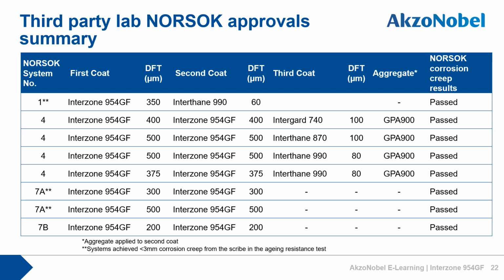This slide summarizes the third-party testing that we have for Interzone 954GF. As you can see from the table, we have approvals for all the key NORSOK systems. System 1 for atmospheric exposure, System 4 for decks, System 7A for splash zones, and System 7B for immersion. The System 1 and System 7A schemes have performed to a level expected of zinc-rich primed systems, which is to say with less than 3 mm corrosion creep from the scribe in the cyclic aging test.